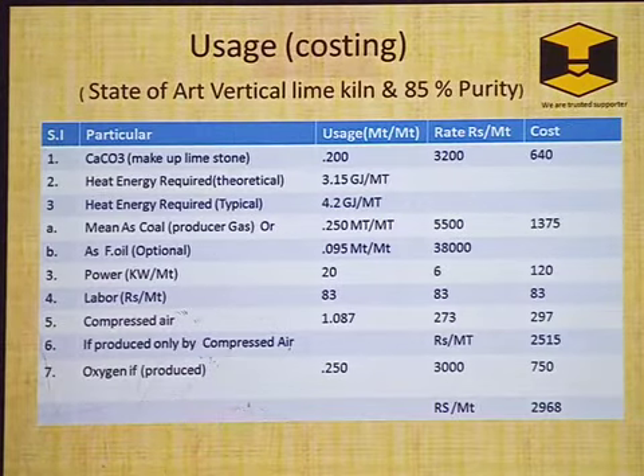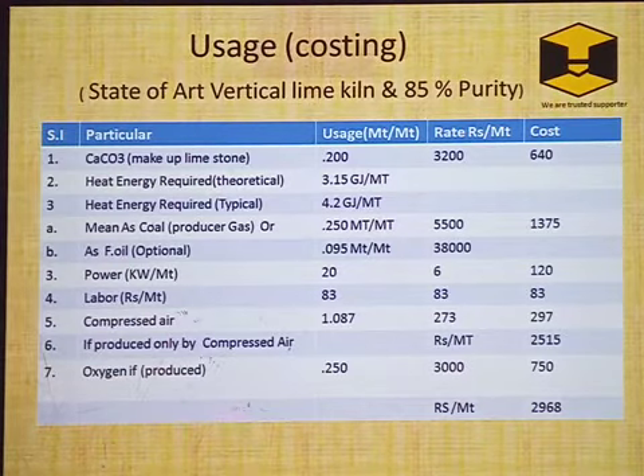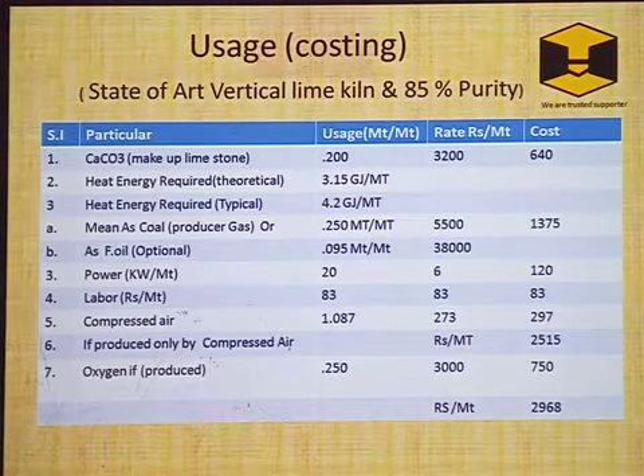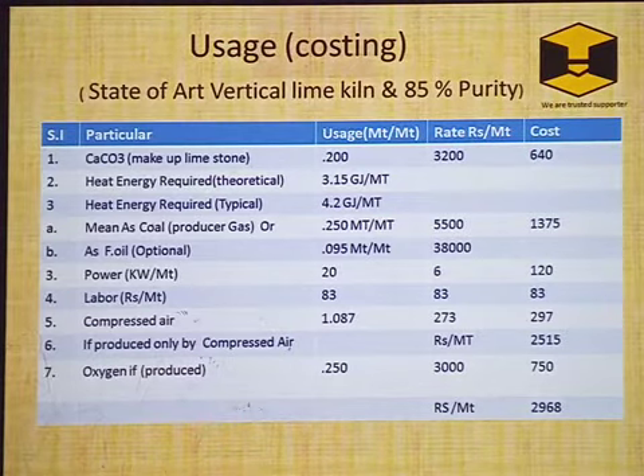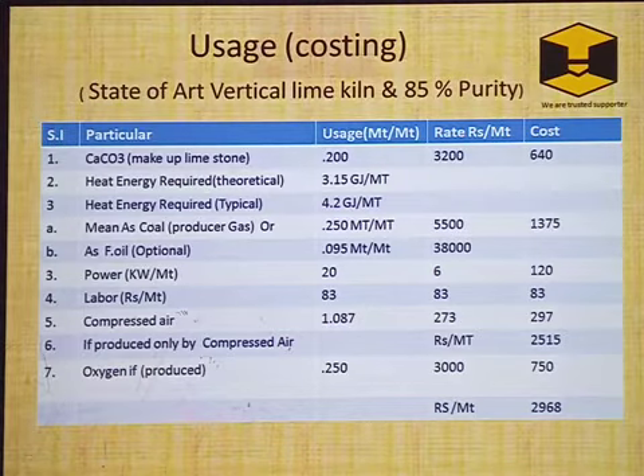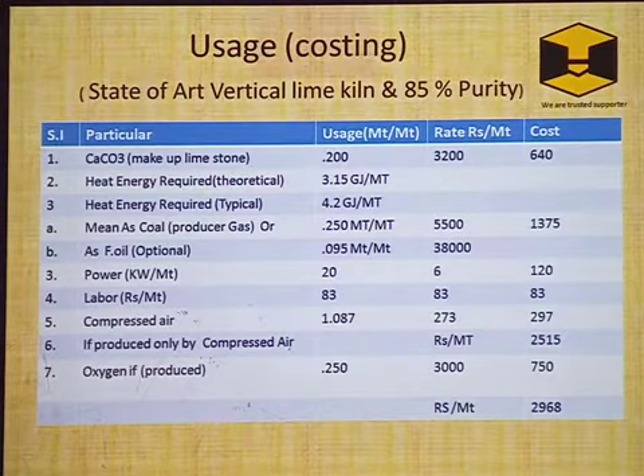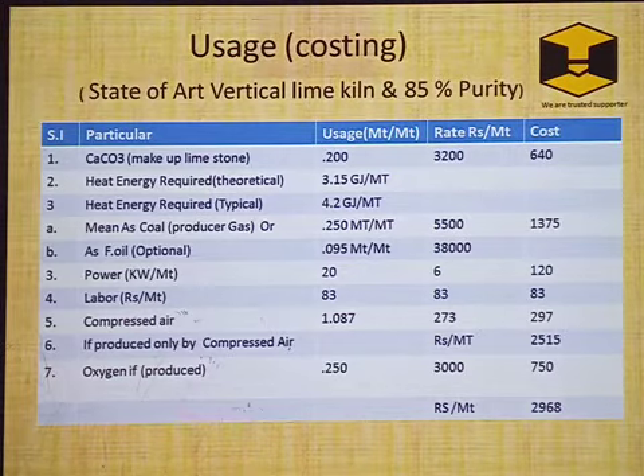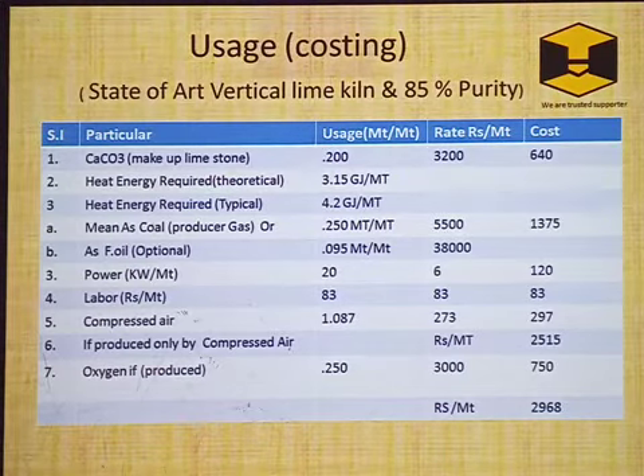Let's see the uses of all the things in the state of the art vertical lime kiln. The state of the art vertical lime kiln claims to produce 85% purity lime at the lowest possible cost. So makeup lime requirement will be 0.2 ton per metric ton, and heat energy theoretically required will be 3.15 gigajoule per metric ton, but typically it requires 4.2 gigajoule per metric ton, which means 250 kg coal as producer gas per metric ton.